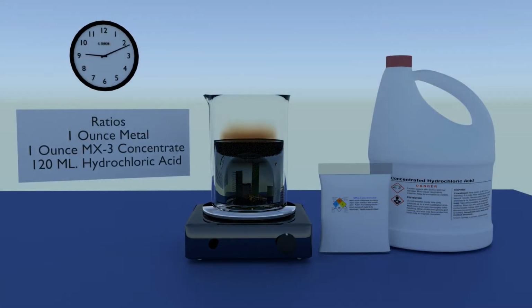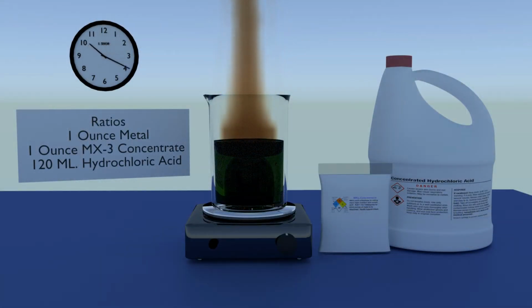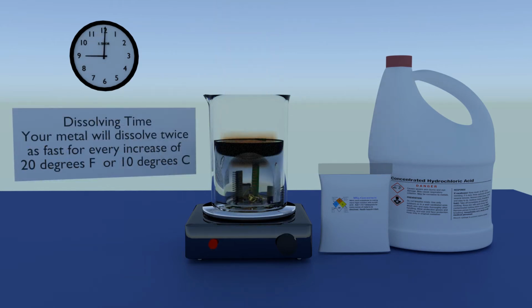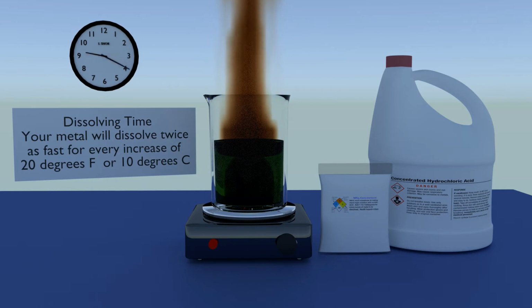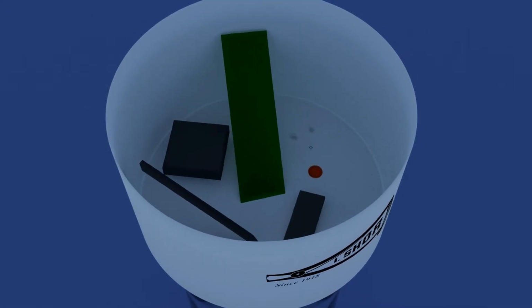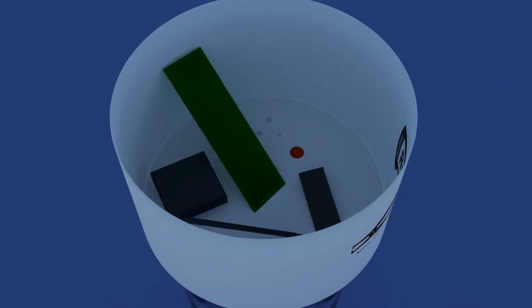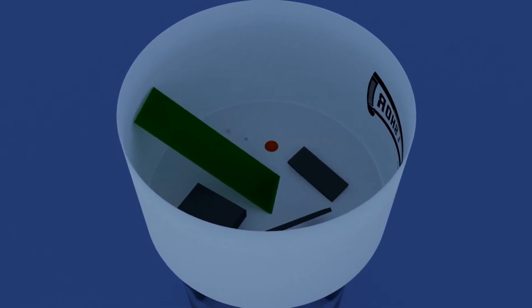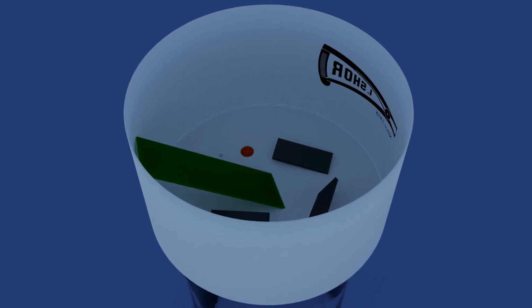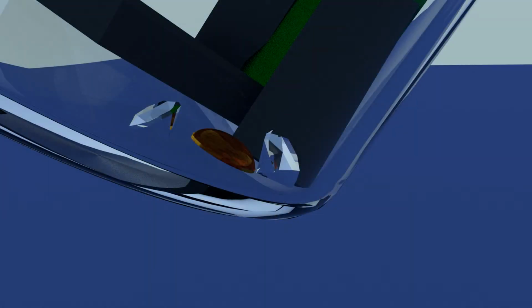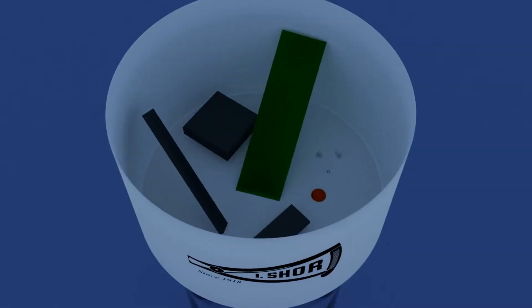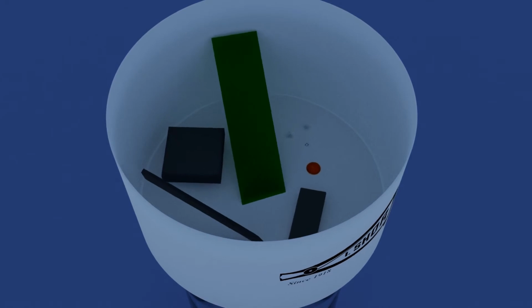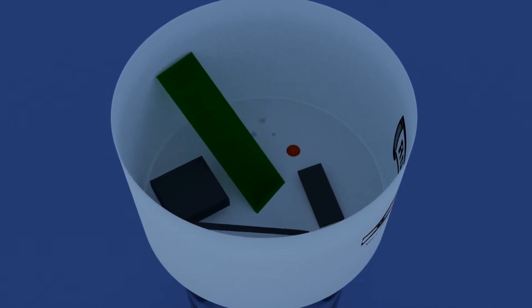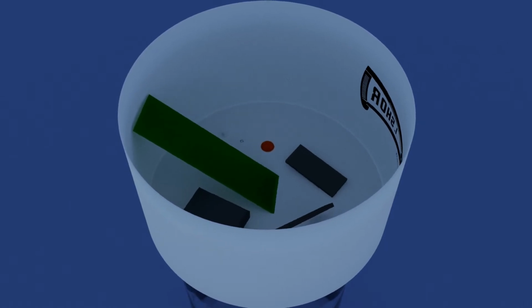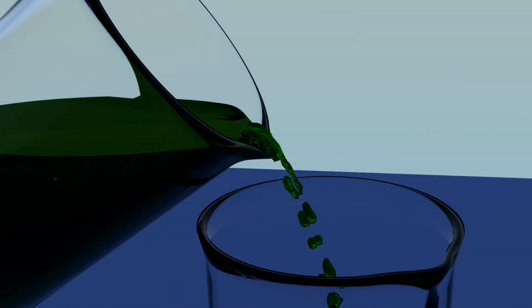At room temperature, your metal will dissolve in about 1 to 2 hours. Heating will significantly reduce dissolving time, but will also significantly increase fume production. After all the metal is dissolved, it is common for some materials, such as stones, ceramics, plastics, etc., to be left behind, undissolved, in either your beaker or your filter funnel. Since those materials would contaminate the gold that you will be retrieving from the solution, you need to extract those materials from the solution before precipitating the gold. This is easily done by either decanting or filtering the solution.